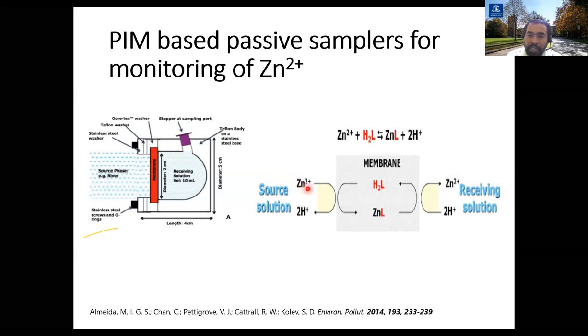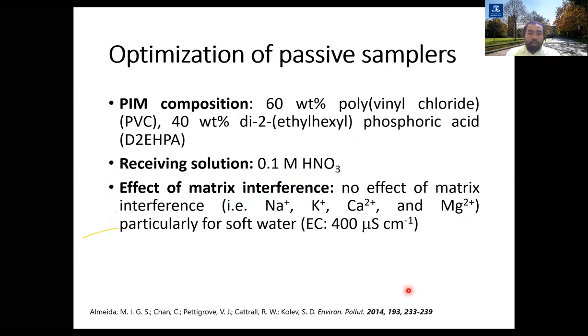So basically what happened is zinc binds to the extractant present in the polymer inclusion membrane, and then diffuses to the other side of the membrane, the receiving solution, where it is exchanged with a proton. This process can occur continuously until the sampling deployment is terminated.